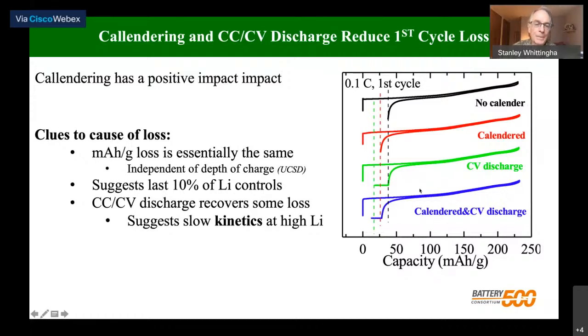So we know some parameters that affect it, and it turns out it's the last 10% of the lithium. So that's from lithium occupancy from 90 to 100%, that's important. And my colleagues in San Diego discovered this by only charging it to say 50%, 40%, 30% of its capacity. It still lost the same 10%. So it's this last 10%. So this is telling us we've got very slow kinetics when we have high lithium content.